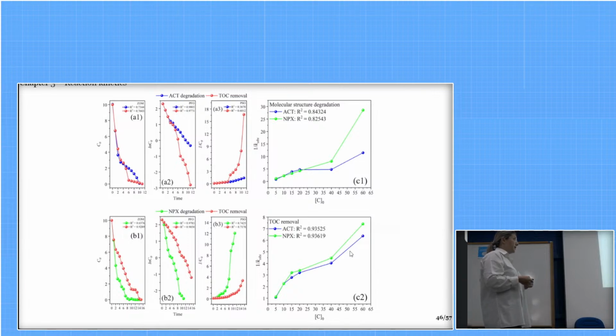So we fitted this again for different pollutant values for the Langmuir-Hinshelwood reaction, and this showed that the molecular structure degradation was not as reliant on surface phenomena as the TOC removal was.